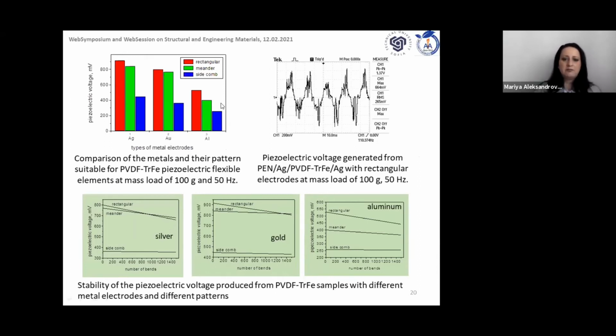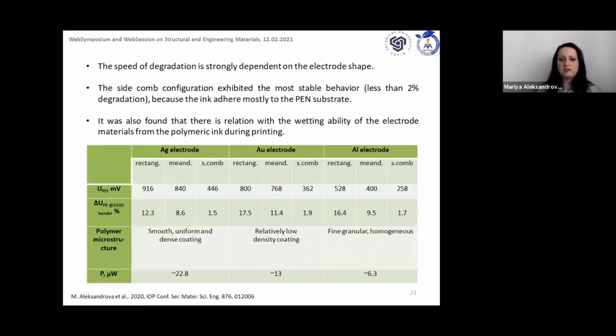Although less voltage is generated from the side comb patterning, we found that it is really stable no matter the kind of metal material, mostly because the piezoelectric polymer is mostly stuck to the plastic substrate rather than to a big area of the electrode itself. Wetting ability of the ink is also important for the performance of the element.